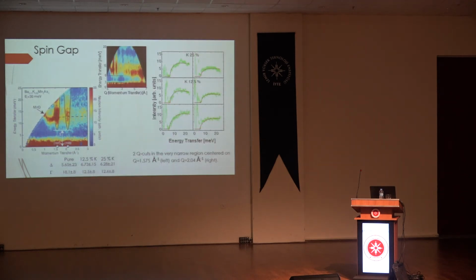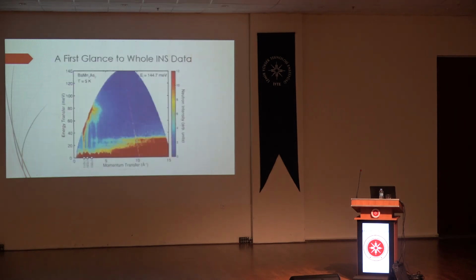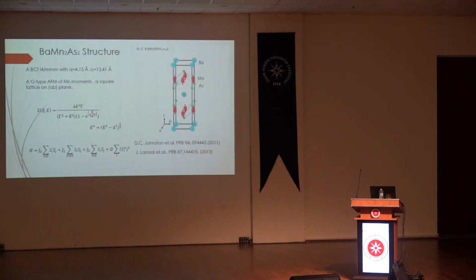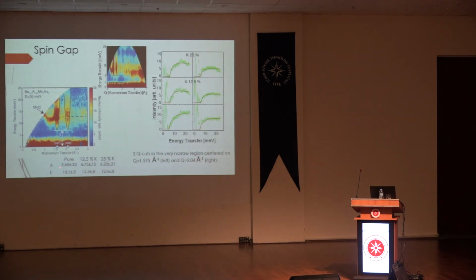Now, for the second damped harmonic oscillator, instead of putting the number over there, we put the phonon background on my magnetic region and define a background. We subtract the phonon background, and also we subtract a Gaussian which is fitted to the elastic line. At the end, we get a two-dimensional order parameter kind of intensity. When we fit those things with this information, the one that I showed over here, we finally get gamma values and sigma values, the spin wave gap.